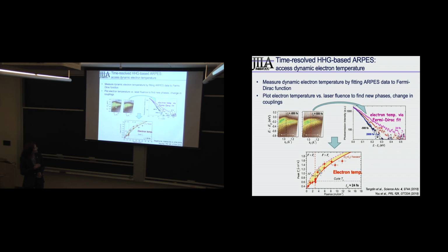We take our ARPES data, do that in a pump probe manner, and fit the electron temperature at every time delay, and then do all of that as a function of laser fluence. And then we plot the electron temperature as a function of laser fluence, and what we expected was to get the purple line, that if you've got a typical electron heat capacity in a metal, you'll have a certain heat capacity. As you pump more laser energy in, you should heat the electrons. But you don't see that. You see that it gets harder and harder to heat the electrons as their temperature approaches the Curie temperature. And this is the temperature measured 24 femtoseconds into the laser pulse. And then once you get above the Curie temperature, it's easier to heat. So this yellow is the energy being pumped into the spin system.